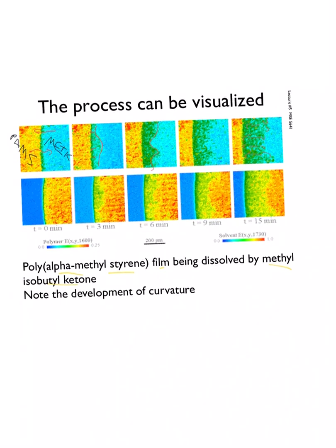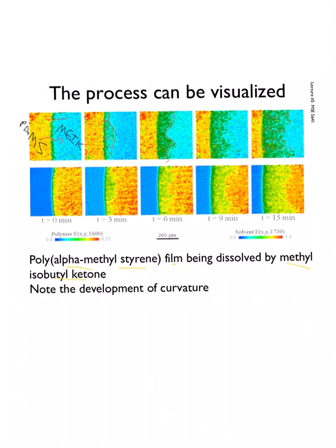And so what you're looking at in this green color is polymer trying to leave the structure, and you can see little bits of green out there and there, where they actually have successfully dissolved and moved out into the solvent. And then you have this region of mixing of the polymer and the solvent at a pretty high level, and there's going to be a gradient in the MIBK that decreases as you move toward that solid. But you can actually visualize this in these structures. And you also see, it's kind of hard to spot, there's a development of curvature, which is the solid reacting to the surface undergoing stress.